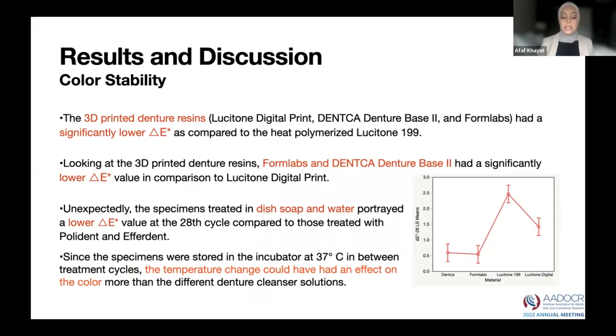Unexpectedly, the specimens treated in dish soap and water portrayed a lower delta E value at the 28th cycle compared to those treated with Polident and Efferdent. Since the specimens were stored in the incubator at 37 degrees Celsius in between treatment cycles, the temperature change could have had an effect on the color more than the different denture cleansers.